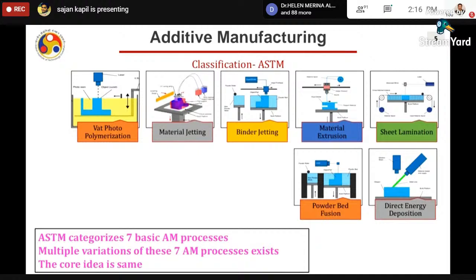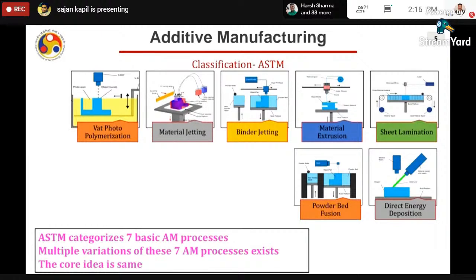In this case, usually if the overhang is less, the loose powder acts as a support material. However, in the case of metal, usually we have to provide the support, and that is because of the residual stresses and warpage in the thin sheets. The last process is direct energy deposition.